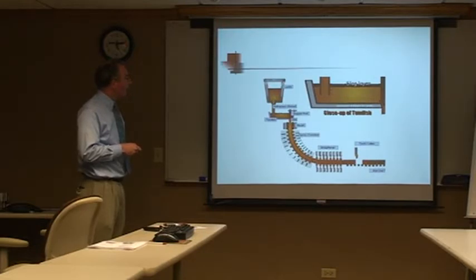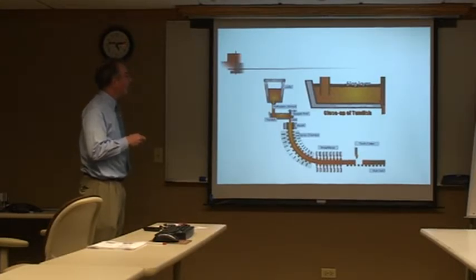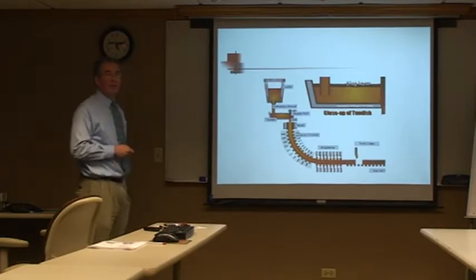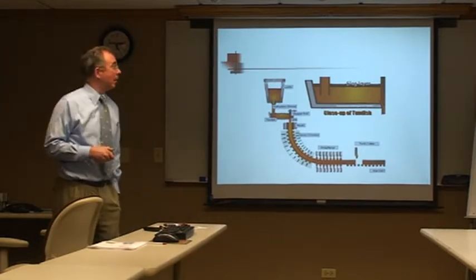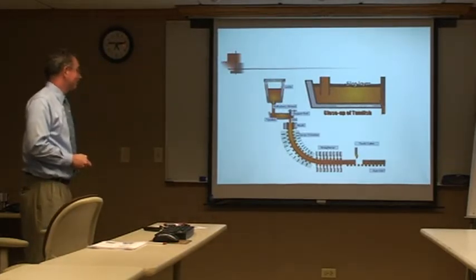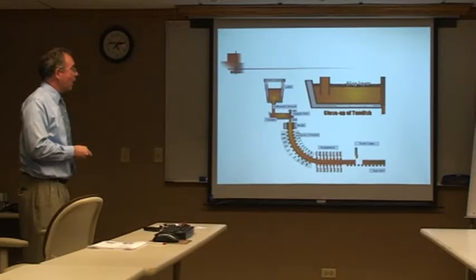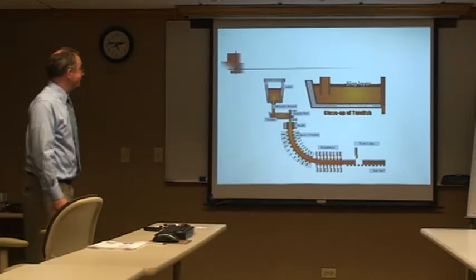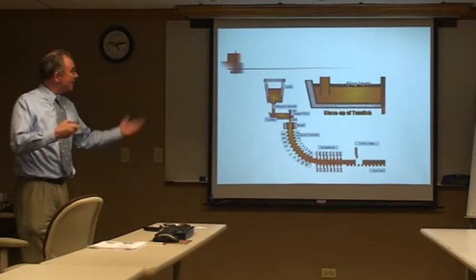It's copper, so you can see here it's bright orange, and as you get further down, you can see this darker orange. I don't know if you guys can see that very clearly or not. You can see this shell getting thicker and thicker until we get down in here, and it's pretty much solidified, and it chops it off. Also here you've got a slag layer covering the bath, so we're not exposing the bath to the air. Usually we'll have a ladle cover here to help keep the heat, minimize the temperature loss during teeming. Spray chamber, again, it's all being done at a controlled fluid. And without going too much, that's continuous casting.